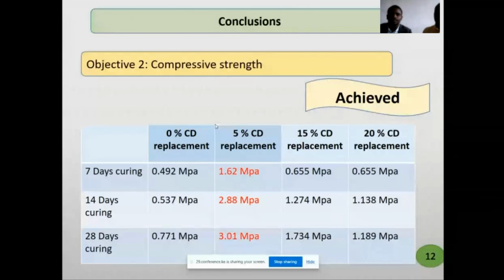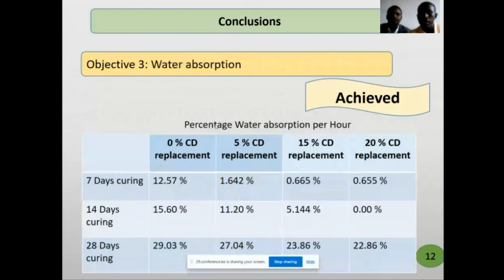Now on the compressive strength, we also compared our 0% replacement, 5, 15, and 20%. And as you can see from the screen, we've seen that the 5% cow dung replacement has a continuous increase from 1.6 to 2.8 to 3.0 from 7 to 14 and 28 days, as indicated in the slide.